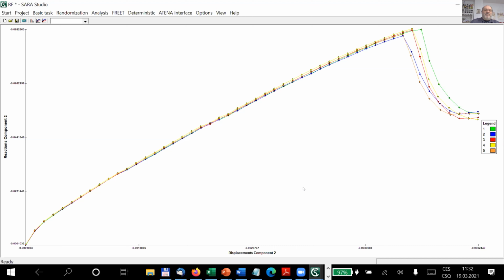if we do the sampling in random variables, we will get the damage picture or the crack pattern very similar, only with different maximum load or different cracking load for each sample. But if we apply these random fields, we will get really different crack patterns because of this distribution, so volumetric or spatial distribution of the material parameters.